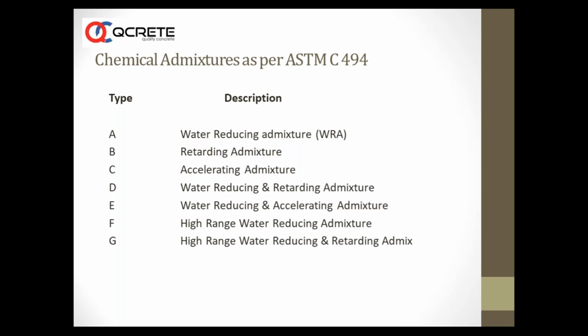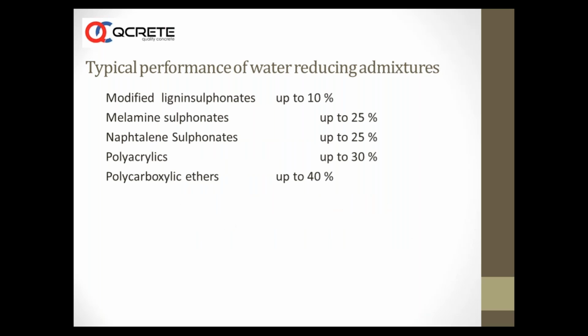The performance of water reducing admixtures based on their basis: lignosulfonates and modified lignosulfonates are up to 10%, melamine sulfonates up to 25% water reduction, naphthalene sulfonates 25%, and the highest has been PCE based admixtures up to 40%.